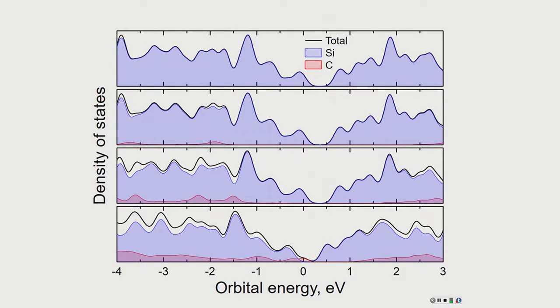Did you plot this directly from the OUTCAR, or did you shift it at all? I shifted it. So where's your HOMO-LUMO gap? For the top three, it's about 0.7 electron volts. For this one, it's like 0.45, something like that. So the top three are open and the bottom one is kind of getting close.